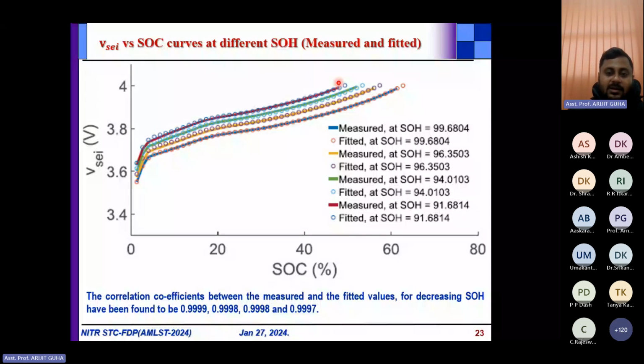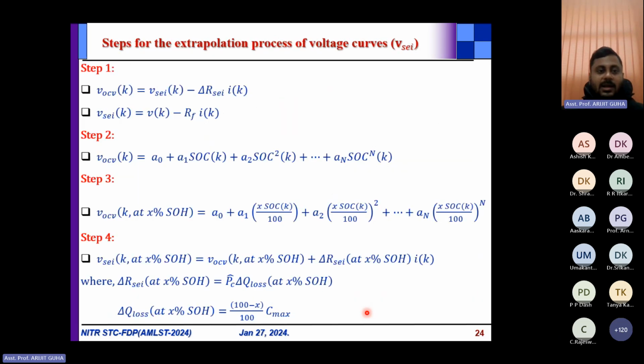In these four cases, the correlation coefficients have been computed and it has been observed that they are very close to 1. You can see here. Now, these are the steps involved in the extrapolation process of the voltage curves, that is the v_sei. We have the initial 400 cycles of data, but we are trying to extrapolate using the electrochemical model equations that I have shown.